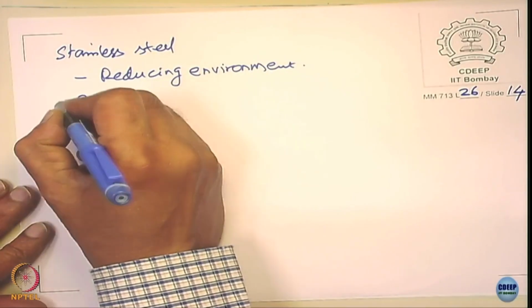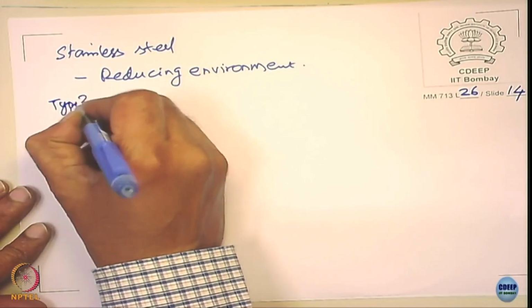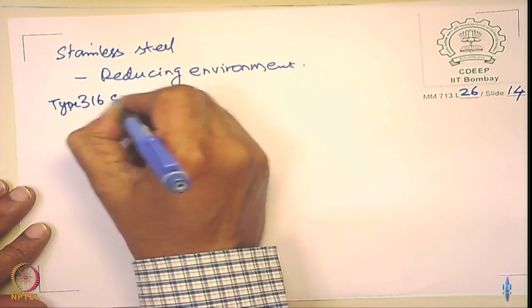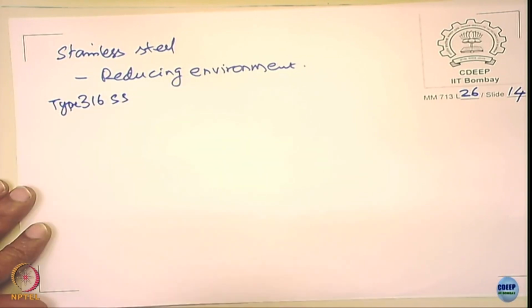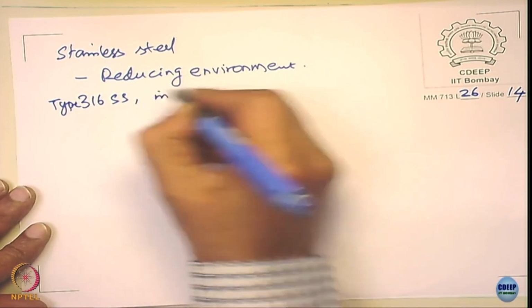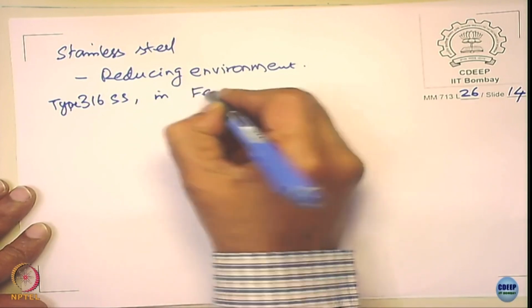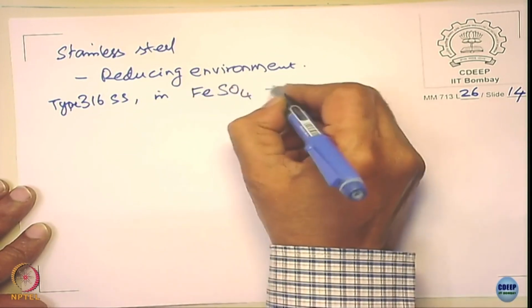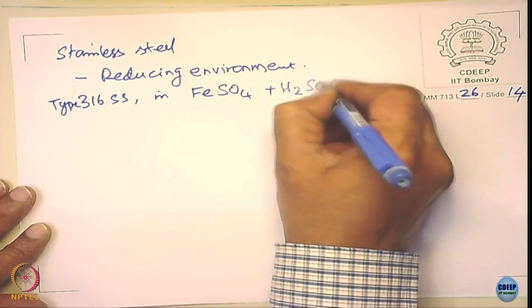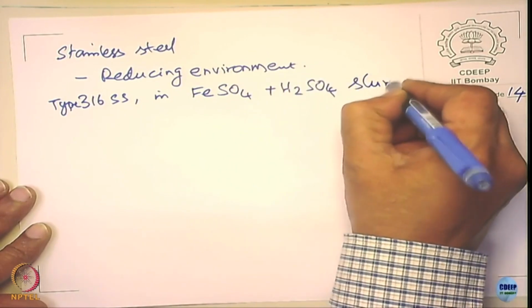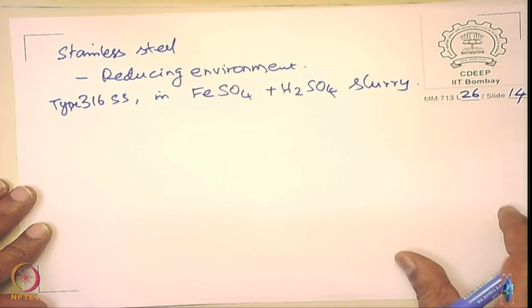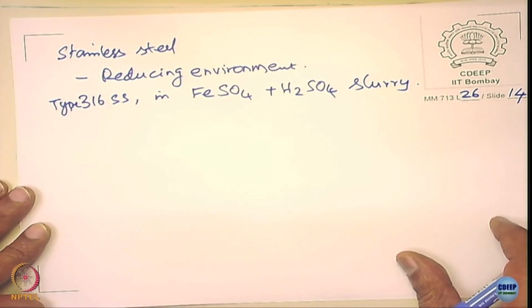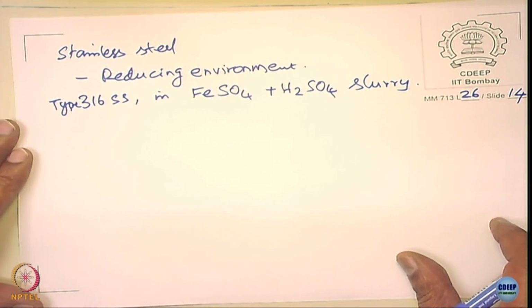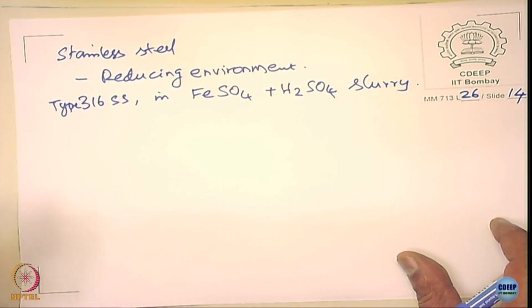That could be seen very well in the case of, let us say, type 316 stainless steels, corrosion in ferrous sulfate plus sulfuric acid slurry. Please notice ferrous sulfate is a reducing condition, not an oxidizing condition. Ferric sulfate is an oxidizing condition.